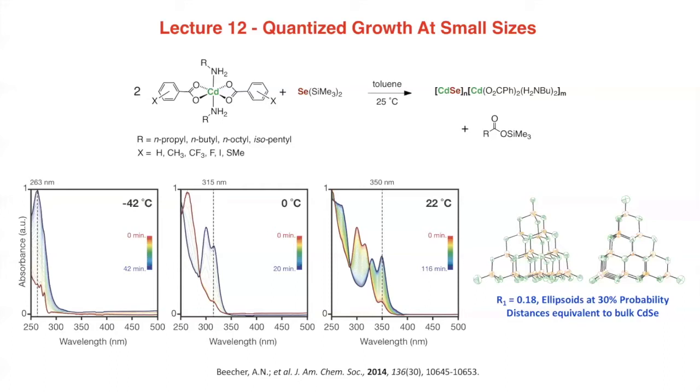At these points, the two objects have the exact same extinction coefficient, and so the sum will always be equal to that absorbance. That tells you that there are no intermediates piling up. It's really just one cluster turning into the next cluster.